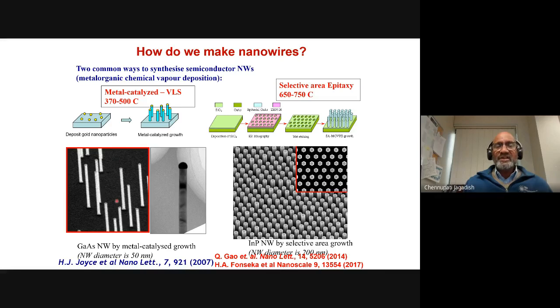To get to that point, she developed a technique called the two temperature growth process. Essentially, to summarize it, she starts the growth at a high temperature, and then after nucleation, she reduces the temperature so it avoids the lateral growth, thereby, instead of creating tapered nanowires, you're able to get beautiful cylindrically shaped nanowires, which are important for laser cavities and other things. But also when we looked at the transmission electron microscope image of these nanowires, we found absolutely no defects, no twin defects and other things which you normally see, and you get atomically perfect nanowires.